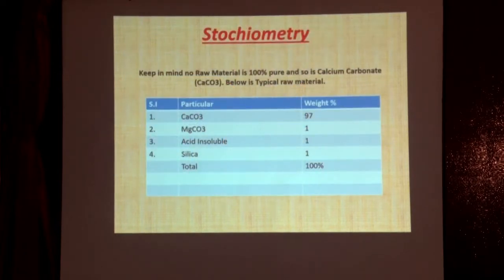This is typically the stoichiometry of the limestone. If you want a very good quality calcium oxide, as Dixit ji has told, silica must be less. But this is the optimal. If you have a raw material mix with 1% silica, it is good enough, because the purer the raw material, the costlier it is. We have to compromise and come to where it is optimal. This is the raw material mix. We have checked this. The calcium carbonate is 97, meaning it is 97% pure. The remainder is non-process, or you can say inerts.